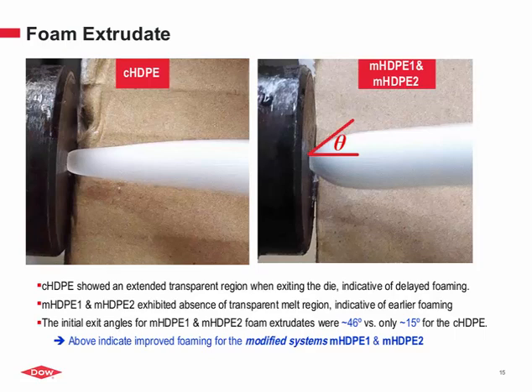Compared to that, both the modified systems do show significantly earlier foaming, which is indicated, number one, by the absence of this transparent region, which is polymer melt. And the second is when we measure the extrudate foaming angle, both modified systems had about a 45 degrees theta angle versus about 15 degrees. That's really 3 times the expansion angle compared to the control system, which is qualitatively indicative of improved foaming for both modified systems.